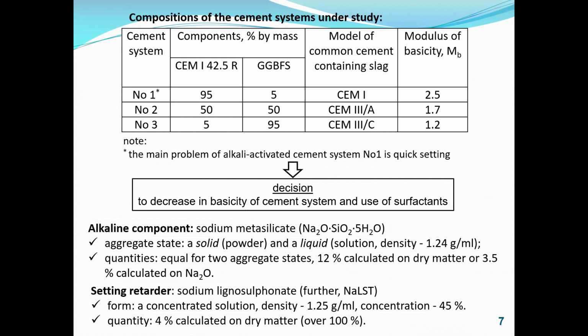Used as an alkaline component was sodium metasilicate in a solid aggregate state and a liquid aggregate state. Sodium metasilicate was added in two aggregate states, both in equal quantities, worth 12% calculated on dry matter. Sodium lignosulfonate was used as a setting retarder in the form of concentrated solution.